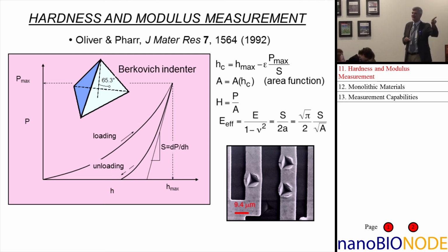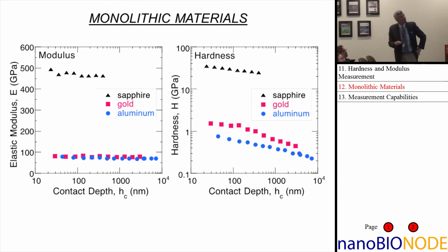So we'll go to the next slide, and that's probably going to be a good place for me to stop the morning stuff. So here are some materials: sapphire, a hard ceramic, gold, a soft metal, aluminum, a soft metal, where we're making these measurements by that series of equations that I showed you. And this is the modulus that comes out, assuming that Poisson's ratio is 0.3, as a function of the depth of contact.